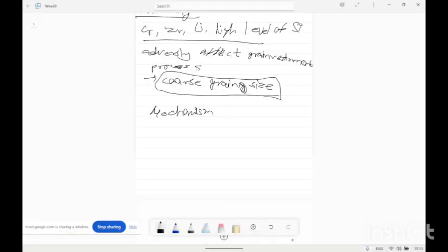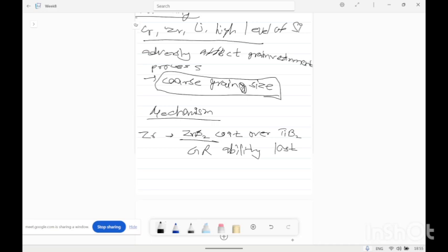So the mechanism of poisoning works as, if zirconium is present, it forms the ZrB2 intermetallic, and ZrB2 coats over titanium boride particles. So by coating of this zirconium boride on the titanium boride, the grain refinement ability of this titanium boride stops or is lost.